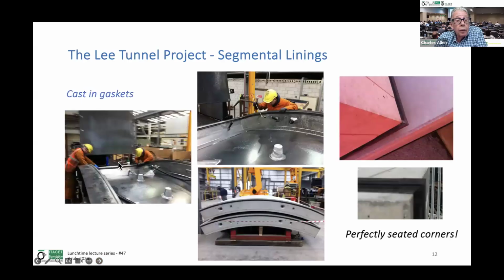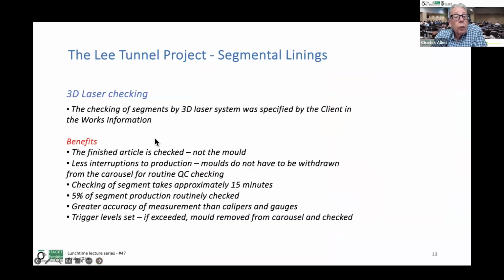Installing the gaskets was quite a simple operation done on the carousel production line, and we checked them with basically a mirror on a stick, like the sort of thing that dentists use when they're looking at your teeth. And those were the finished segments, and the benefit was we got perfectly seated corners that you don't always get with glued gaskets. We specified, and I actually drafted the specification for the segments for this project, the 3D laser checking of segments using a 3D cloud system.